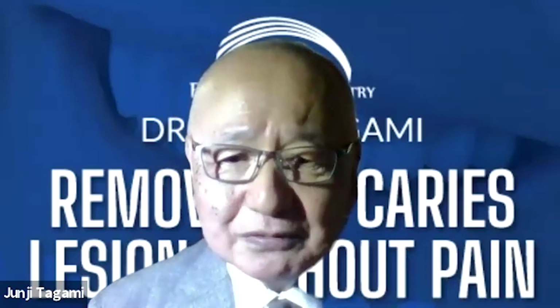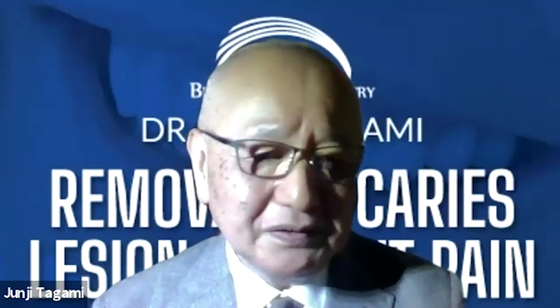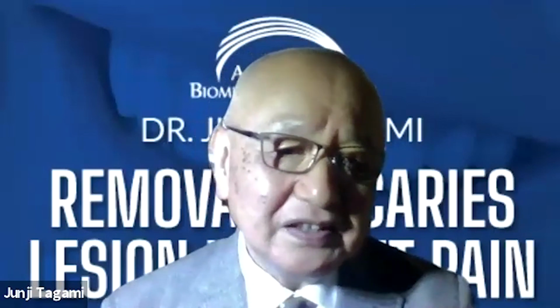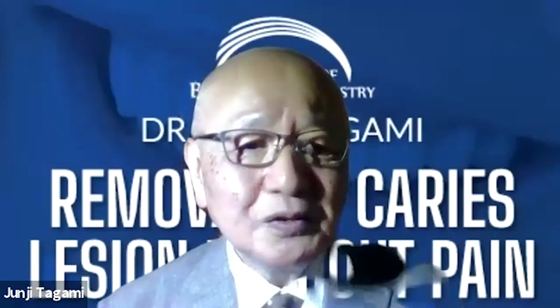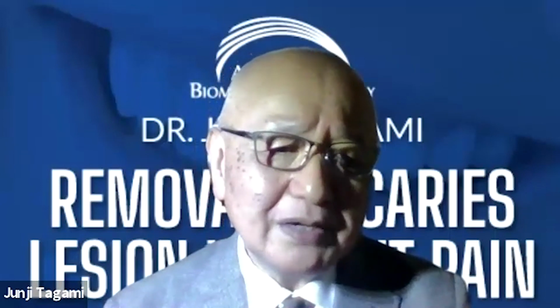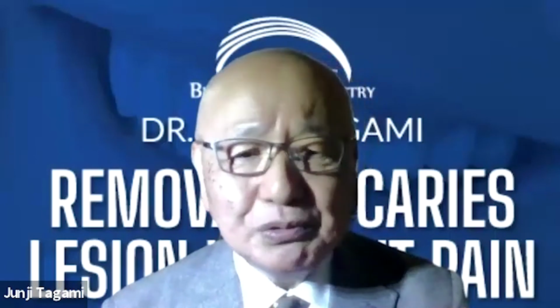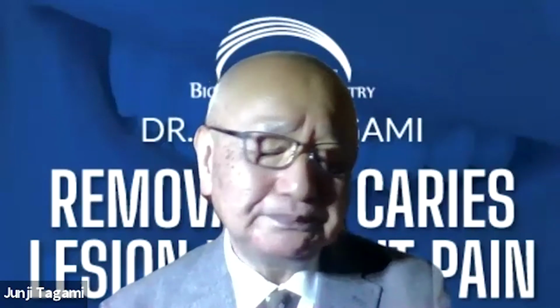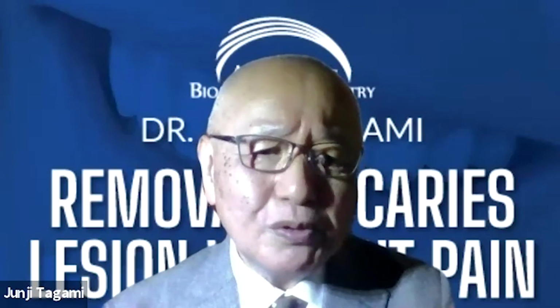So in the case of repair, of course, we need to bond the composite to enamel, dentin, and all the restoration surfaces. And in that case, of course, the cut composite resin material is also covered by the composite smear layers. To clean that surface, the phosphoric acid treatment is very effective. So that's why I try to apply the phosphoric acid to the material surface and the enamel surface together. Then rinse and dry, and then we apply the self-etching primer onto the whole surface.